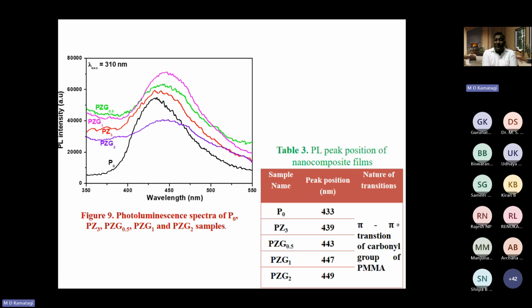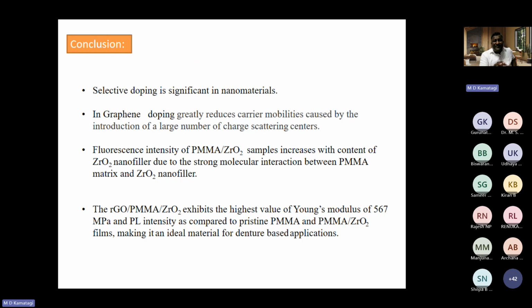One should remember that dopant should be as minimum as possible. Usually the doping is 1 part in a million. If the doping concentration increases, the host material loses its own properties. So clearly, the selective doping enhances the mechanical properties, the electrical properties, as well as the optical properties of the composite films as well as the atomic layers. With this, I wish to conclude this session that the selective doping is significant in nanomaterials.